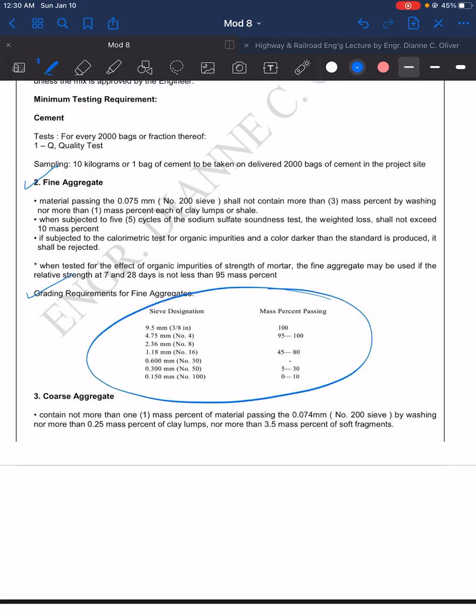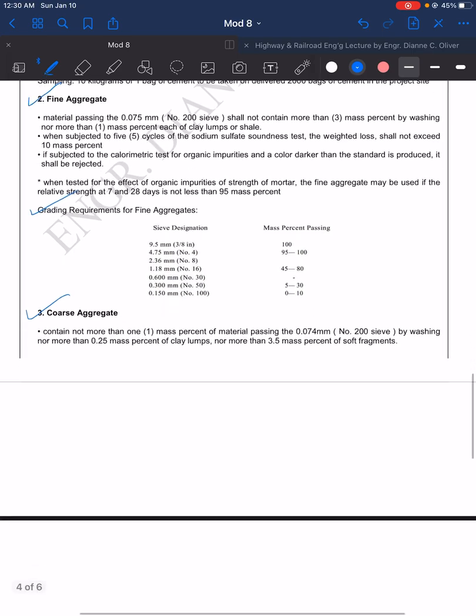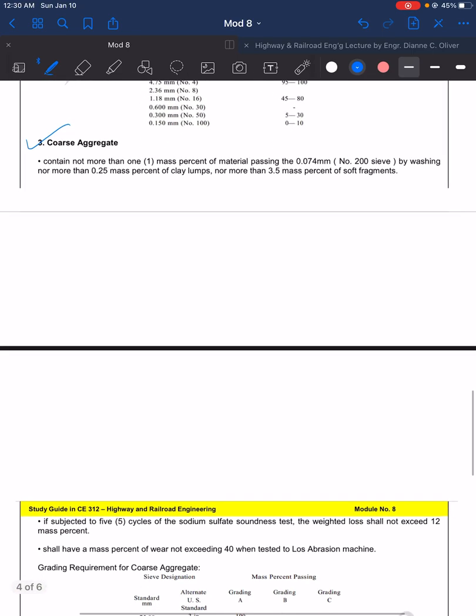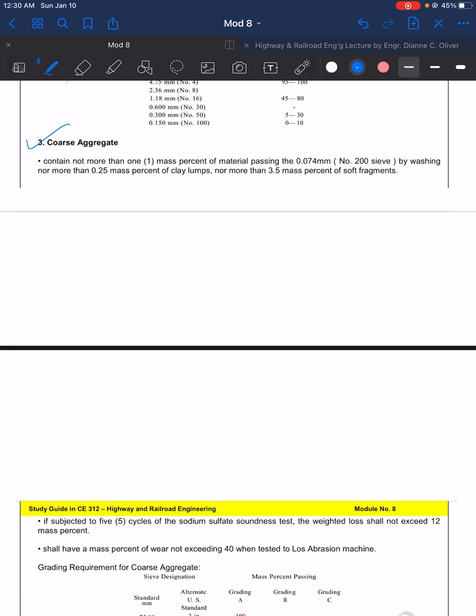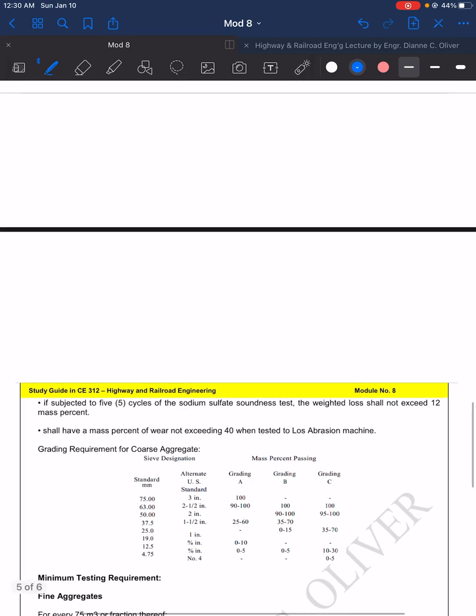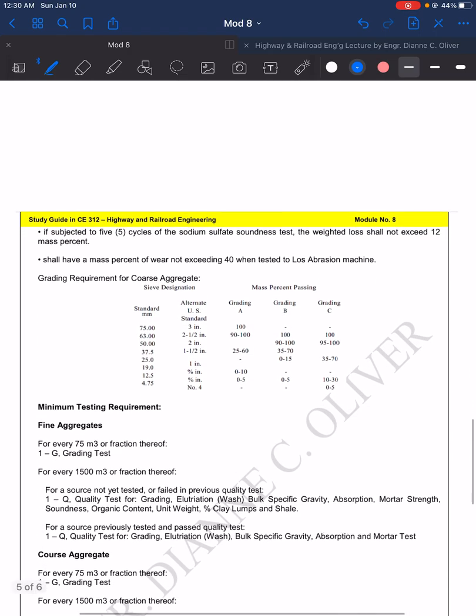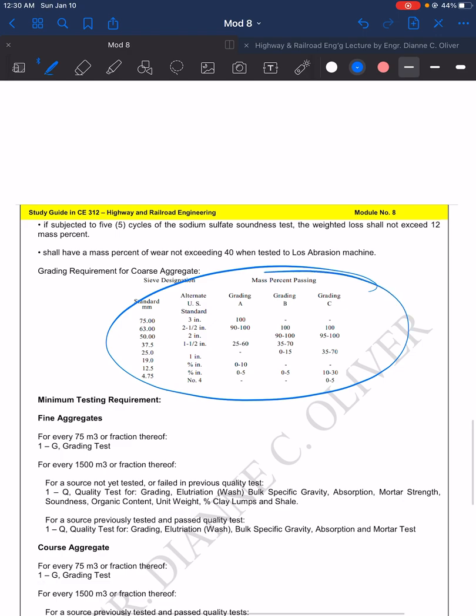For the coarse aggregate or the gravel, it shall not contain more than 1 mass percent of material passing the number 200 sieve by washing, nor more than 0.25 mass percent of clay lumps, nor more than 3.5 mass percent of soft fragments. So for the stones, it is warning again for the presence of clay and soft fragments that are not classified as stone. And then for the grading, these are the grading requirements for coarse aggregate.